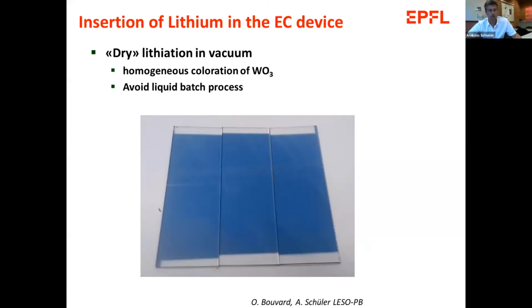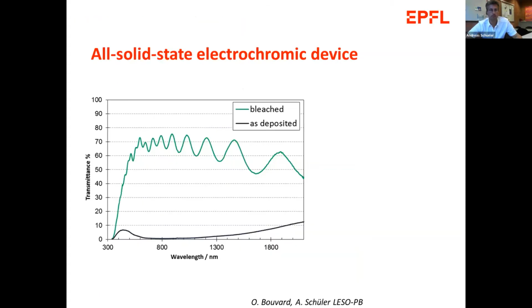So we need to get the lithium into the system. So Olivia developed a lithiation process for that purpose. So we have now a process in order to lithiate our coatings in the vacuum system. So we would start by depositing a tungsten trioxide layer and then inserting the lithium here by a special resublimation process. So this is important to fill up the device with lithium, and then we would continue and build up the other layers so that the lithium is contained in the multi-layered system.